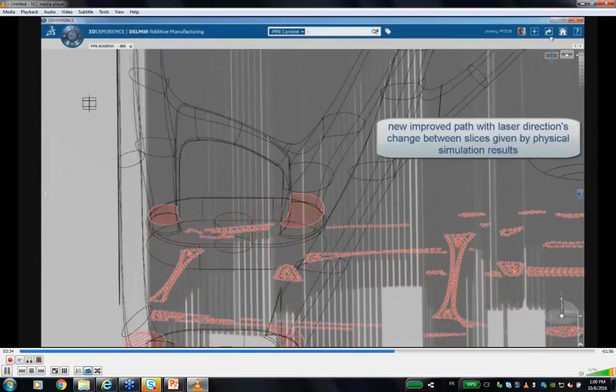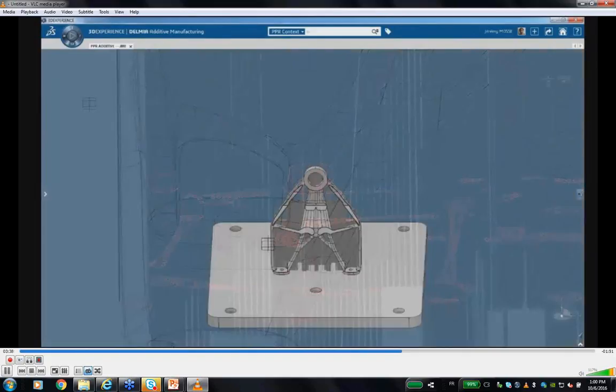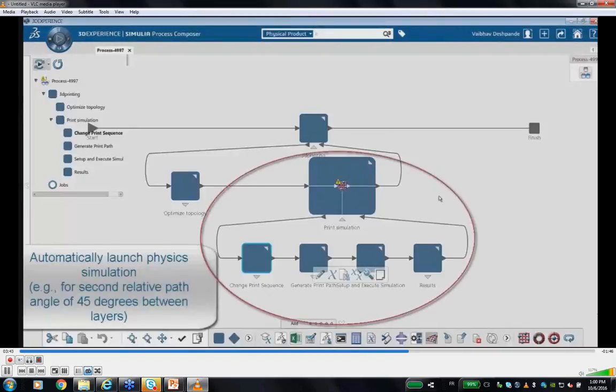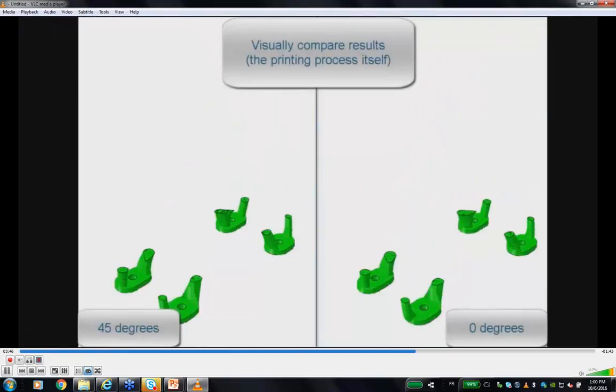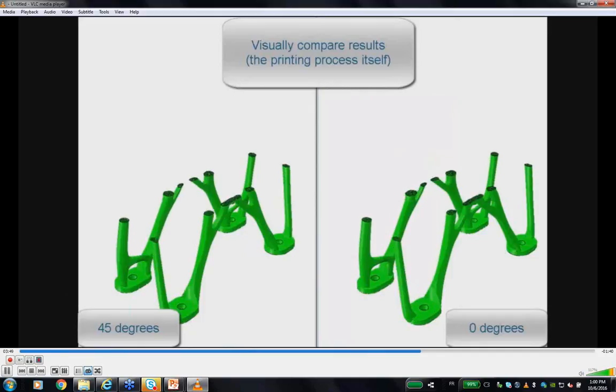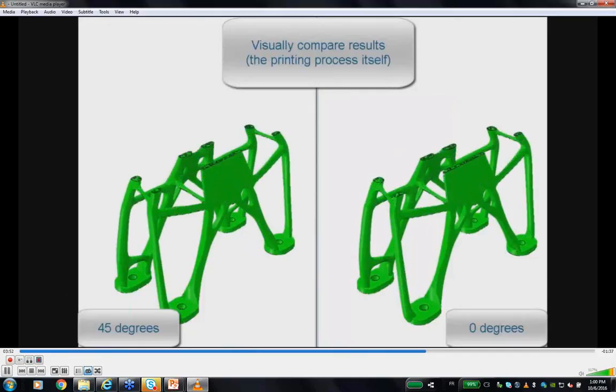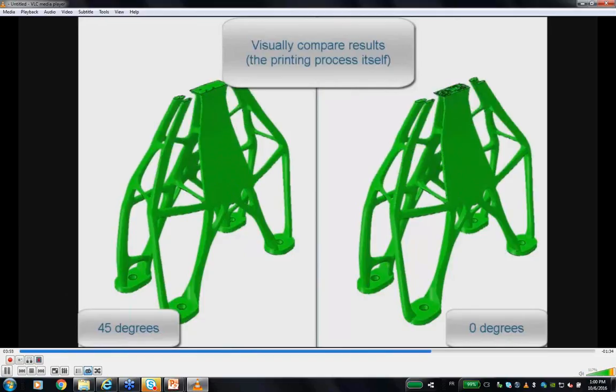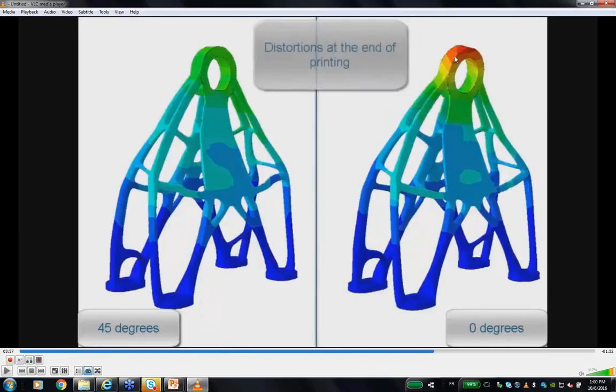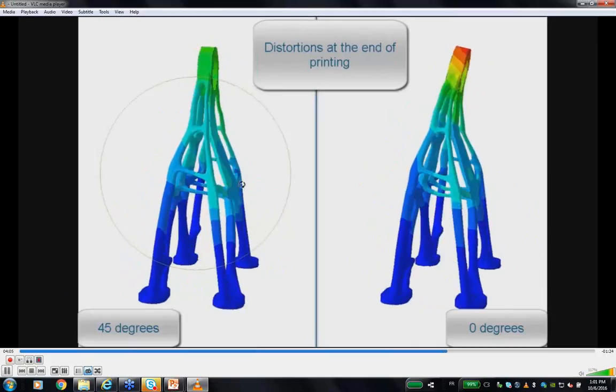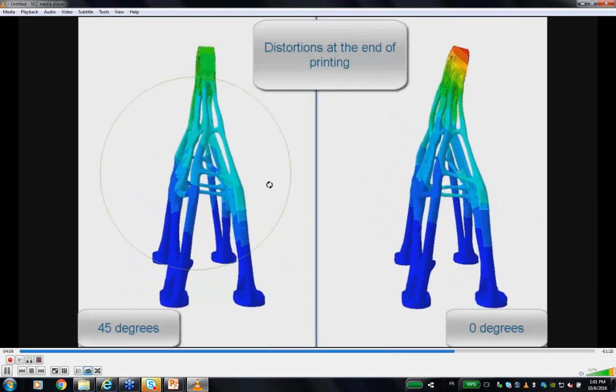Okay. So now we will recompute the analysis. So thermal analysis, residual stress, and now we can compare the two options, without rotation on the right, with rotation by 45 degrees every single layer, and check what is the best solution. Okay. Typically, you can see that here we have a lot of distortion and a lot of stresses, which is less the case in this particular area. We can even imagine that we ask the system to really compute the best option, the best angle to minimize the distortion. And of course, the distortion might occur, but it should be controlled and within the specification of the part. So here, obviously, on the right, it's too much. On the left, it looks like acceptable.